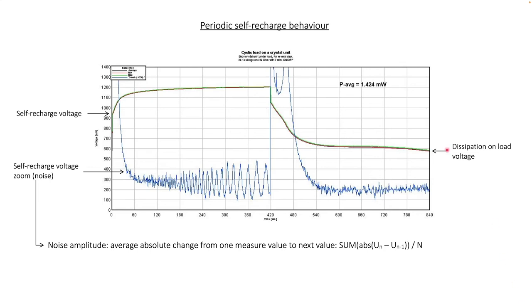We see that when switching the external load on, then first the voltage drops immediately down. Then we have some dynamic behavior here until the output reaches a certain level that can be maintained over several minutes. Then when switching the load off, we get to the beginning here, and we see that the voltage on the crystal cell recharges itself, first a bigger jump and then some dynamics after it then tunes in to the previous voltage level.